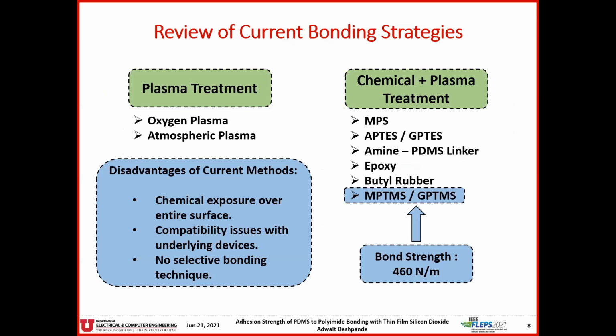Direct bonding of polyimide and PDMS results in poor adhesion between the two. Plasma treatment alone or combined with other chemical treatments are used for improving the adhesion strength of the bond between PDMS and polyimide. Some chemicals used in literature are APTES, MPS, butyl rubber, epoxies, etc. Surface treatment with a combination of MPTMS and GPTMS followed by plasma treatment produces the best bond strength of 460 newtons per meter as found in literature.